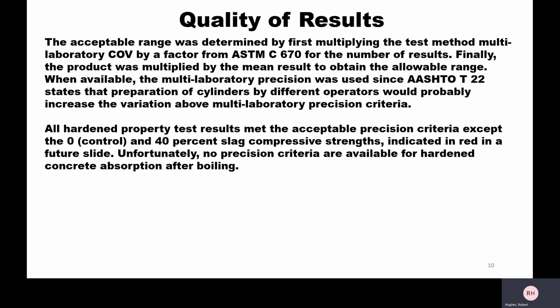Okay, so the acceptable range was determined by first multiplying the test method multi-laboratory COV by a factor from ASTM C670 for the number of results. Then the product was multiplied by the mean result to obtain the allowable range. And when available, we use the multi-lab precision factor because AASHTO T22 states that preparation of cylinders by different operators would probably increase the variation above multi-lab precision criteria. Now, all of our hardened property test results met the acceptable precision criteria except the 0% substitution and the 40% substitution, and that'll be indicated in a future slide. And also, there is no precision criteria available for hardened concrete absorption after boiling, so there is no comparison there.